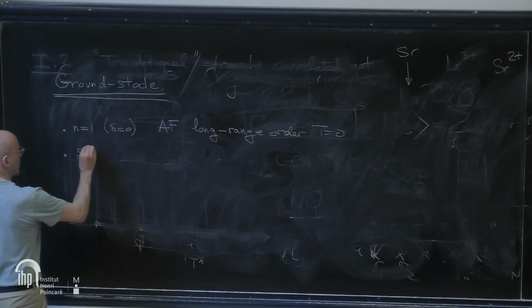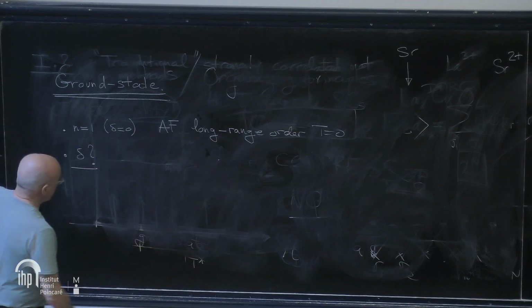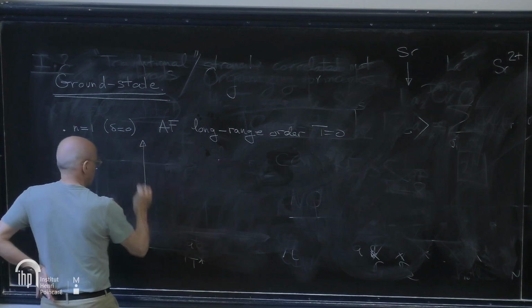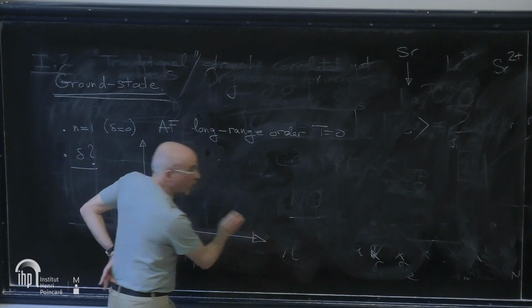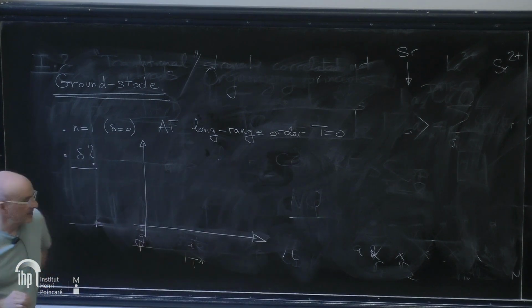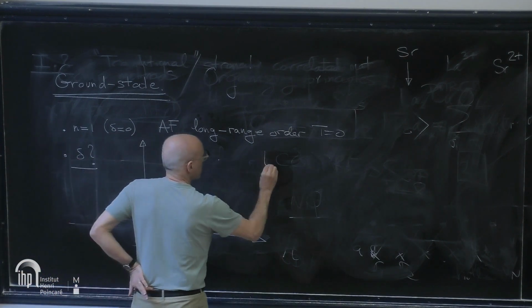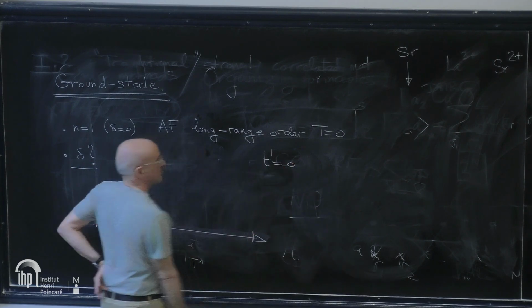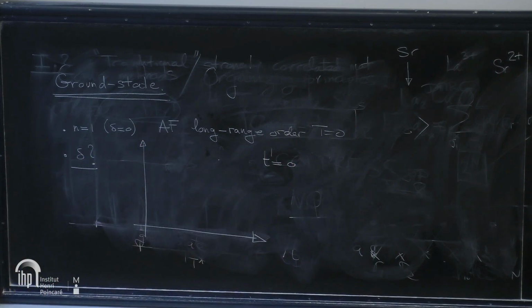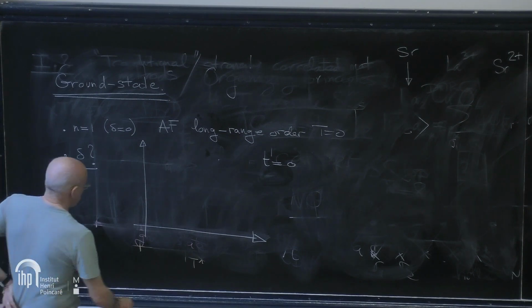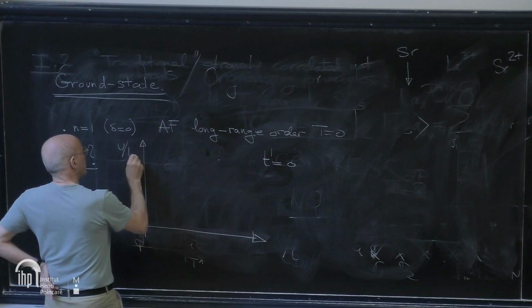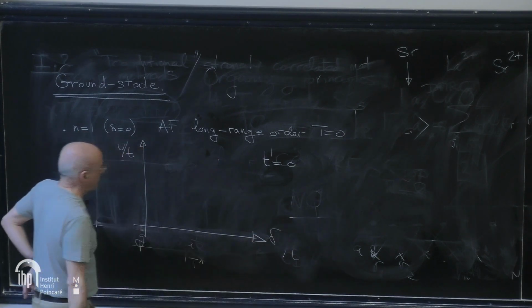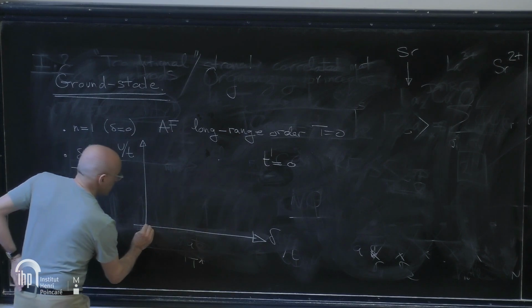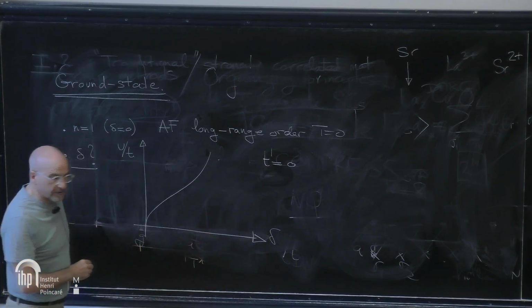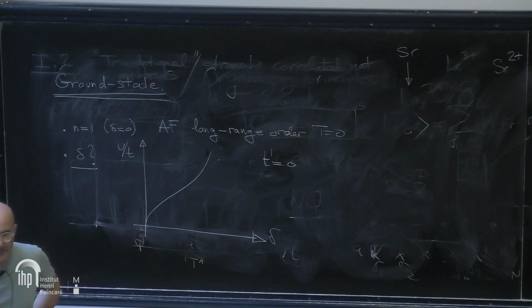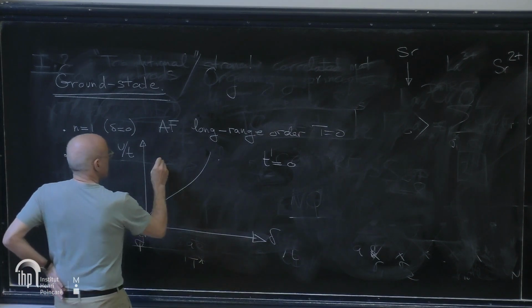Now, what happens when we dope? When we dope, it's been now essentially established by all methods that if there is no t prime, I remind you t prime is the next nearest neighbor hopping, the ground state at low doping, so this would be U over t and doping, the ground state at low doping has both charge order and spin order in a pattern which is called stripes.